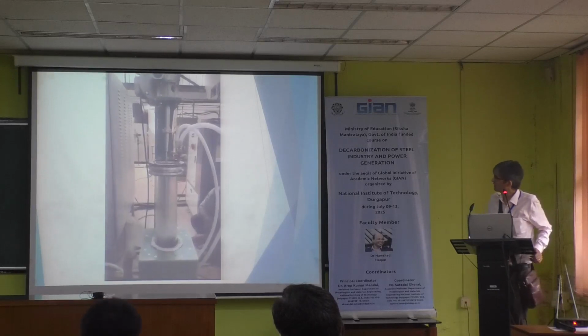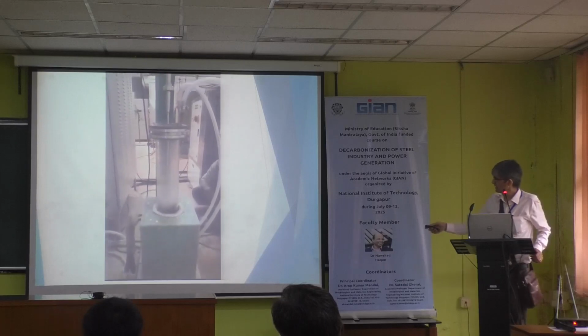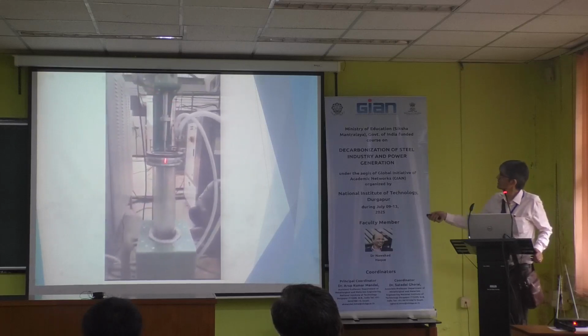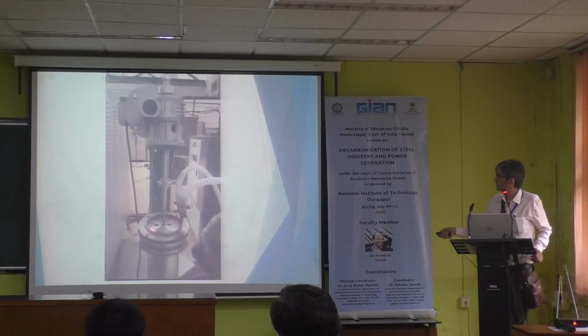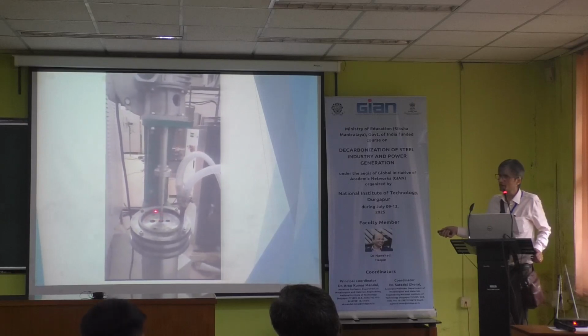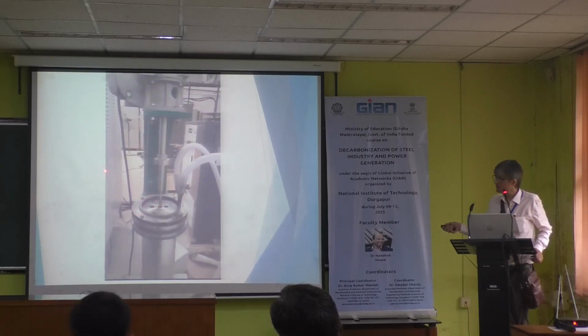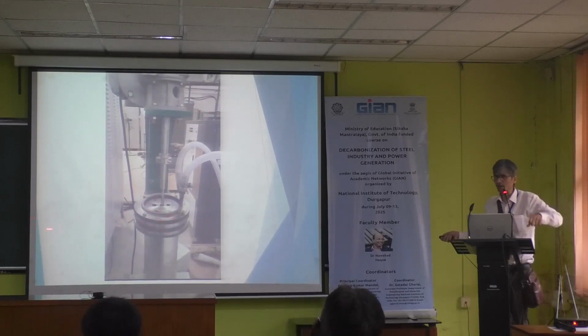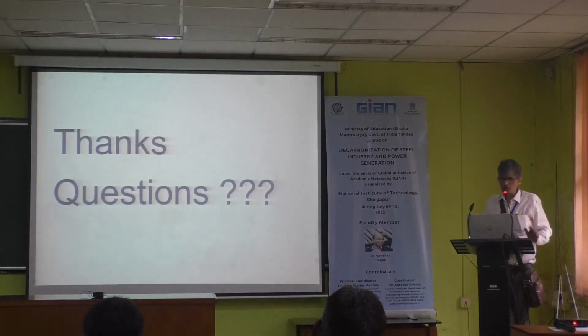Just for example, this is how the setup looks in actual sense. Here the cylinder is rotating, and from here we can control the RPM. There are a number of ports; for example, one port would be for argon, so you can create an inert atmosphere inside. We can also insert a rod for sample taking at different time intervals, so the melt sample could be taken and characterized later on. So this was all about it.